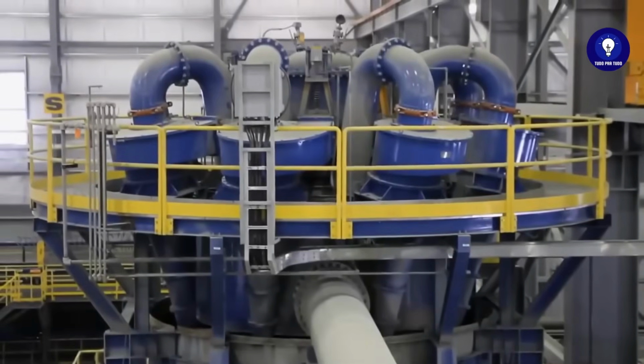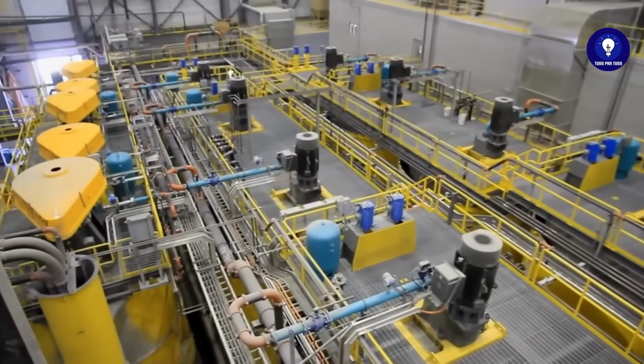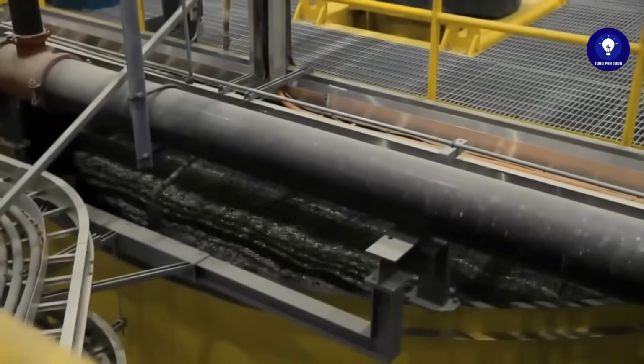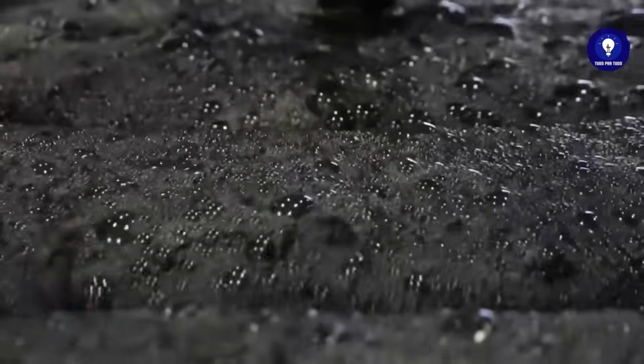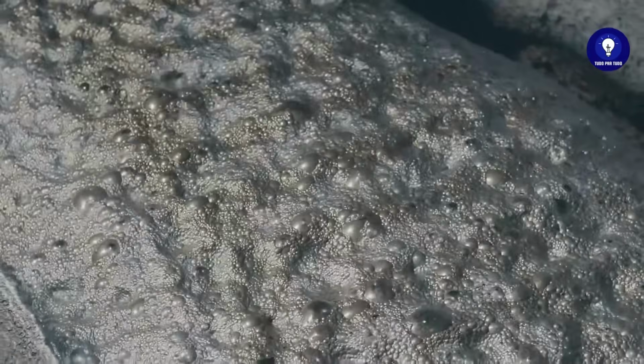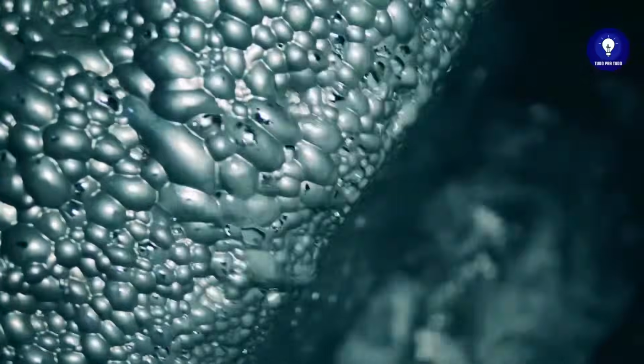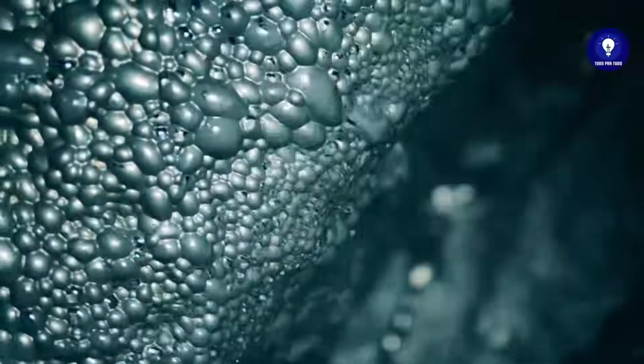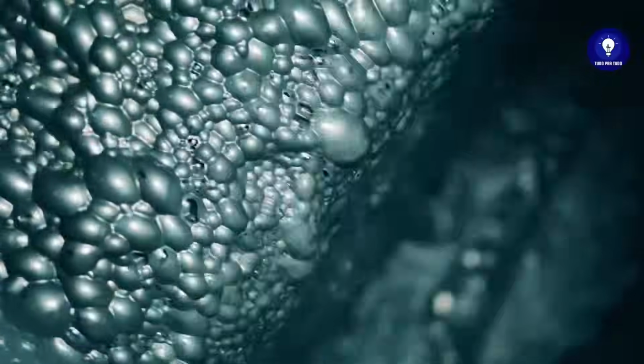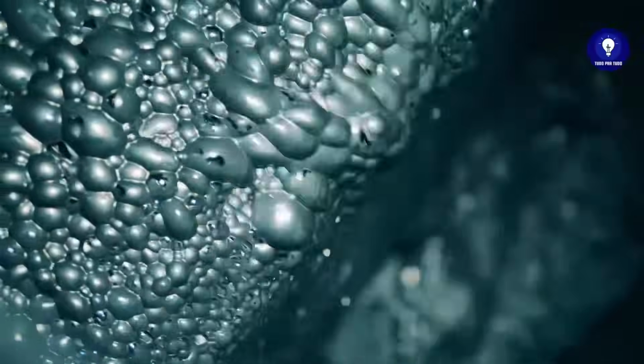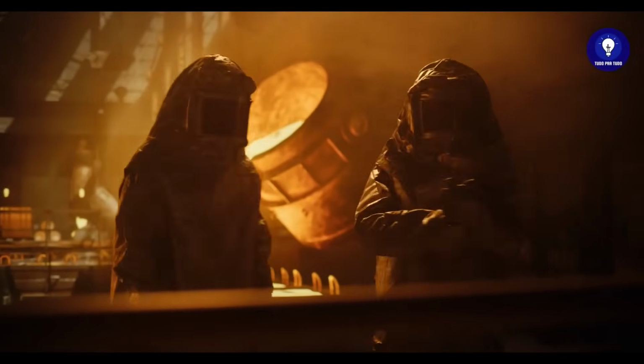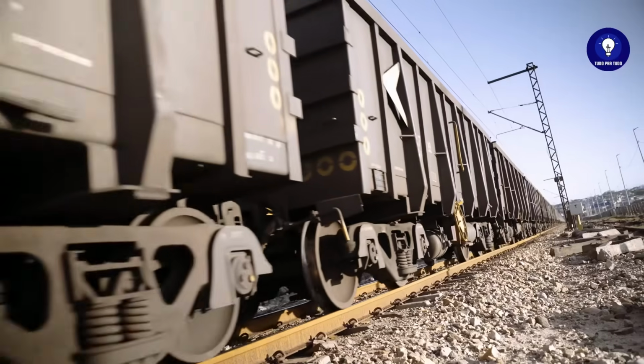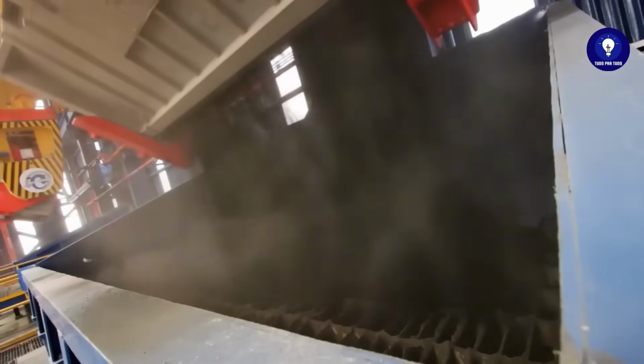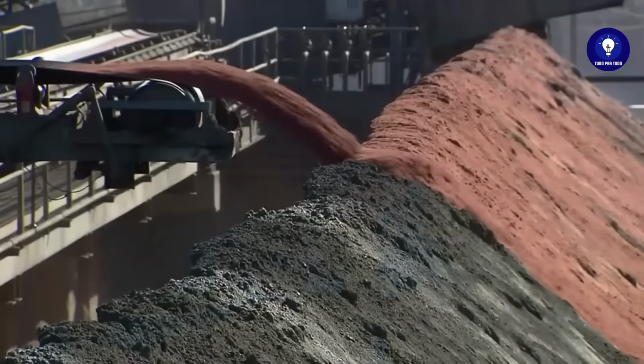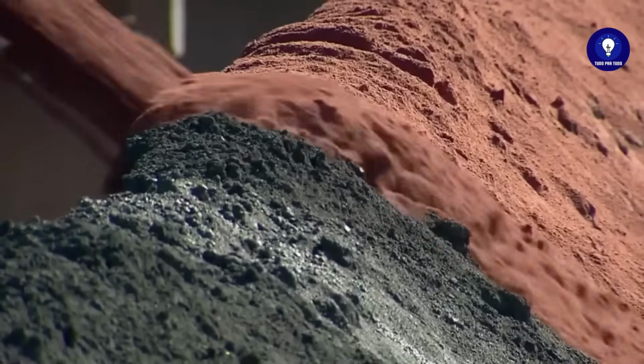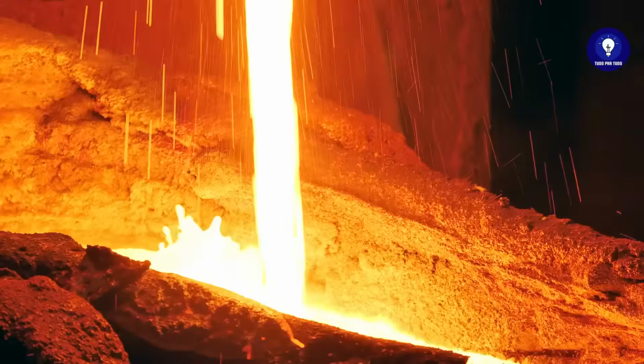Once pulverized, chemicals are added that coat the copper particles, and a foaming substance is mixed in. The mixture enters the flotation tanks, where air bubbles carry the particles to the surface. This copper-rich foam is collected and filtered to obtain a concentrate with a purity of at least 30%. The next step takes place at the smelting plant. The concentrate travels by train to huge yards, where it is layered with silica sand, known as flux. This sand helps remove impurities during smelting.